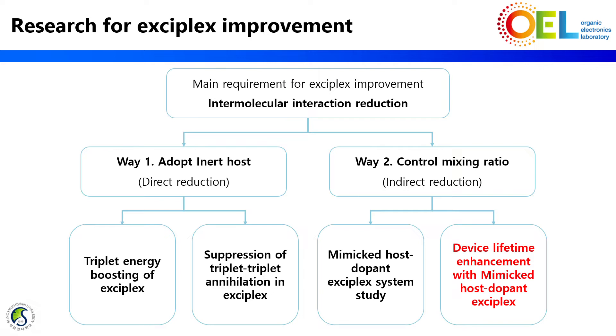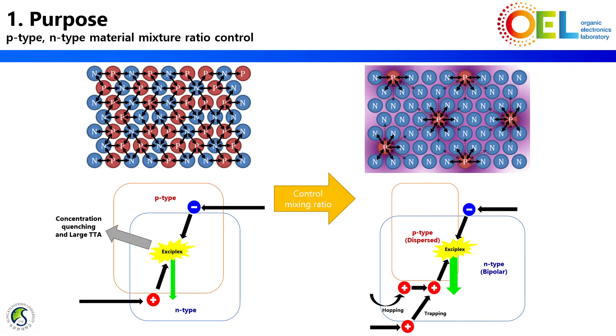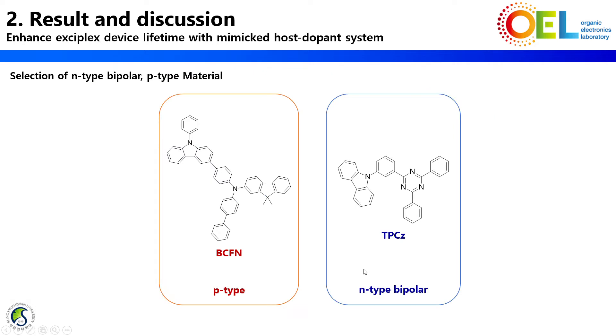Now, in the last chapter of our Exciplex research, the lifetime enhancement effect will be confirmed in the Mimicked host-dopant Exciplex. The overall process was the same as the previous work. By this ratio controlling, Exciplex was dispersed, then intermolecular interaction between components of Exciplex would be reduced. Due to this, concentration quenching and TTA effects also become suppressed. But this suppression effect brings not only device efficiency improvement, but also stability improvement. So we will confirm the lifetime enhancement effect with this Mimicked host-dopant system.